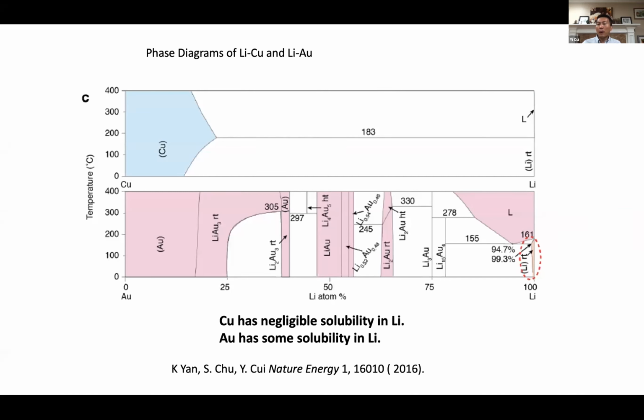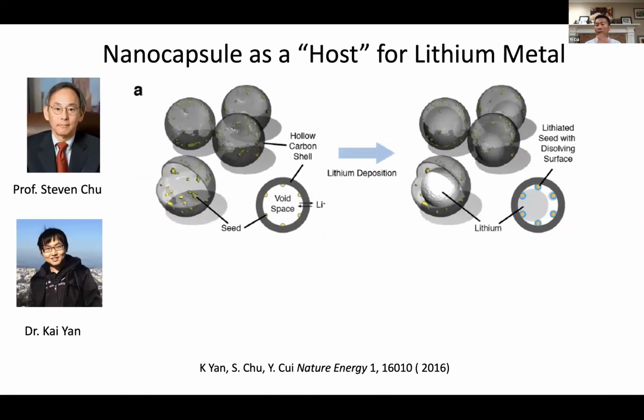Lithium and copper have different crystal structures, so nucleation of lithium on top of copper has a nucleation barrier. Lithium dissolves gold away, making gold more and more look like lithium, so there's no nucleation barrier right there. If that is the case, we could use different materials to control where lithium would like to nucleate. That underlines the powerful concept of nucleation into a host.